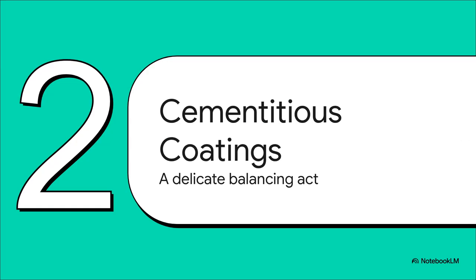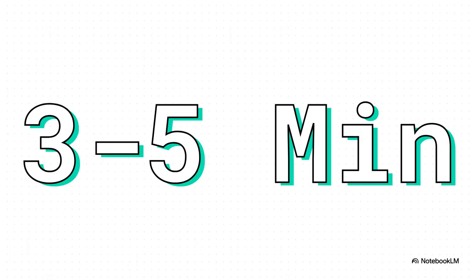Let's start with the most common one out there: cementitious coatings. These things are workhorses. They're incredibly effective, but you have to respect the mixing process. It really is a delicate balancing act. So what are we aiming for? What's the magic number? For most cementitious products, you're shooting for a mix time of about 3 to 5 minutes, and you've got to use a low-speed electric mixer. Your goal is a perfectly smooth, lump-free consistency. That right there, that's your window for success.